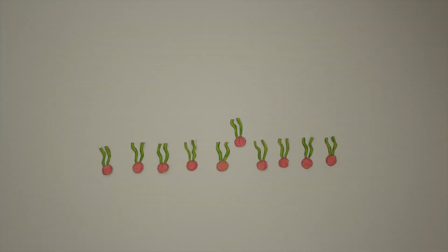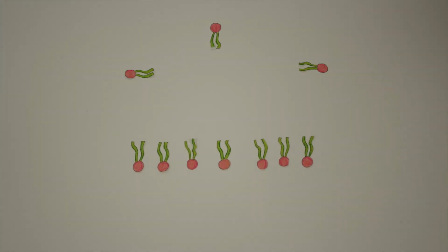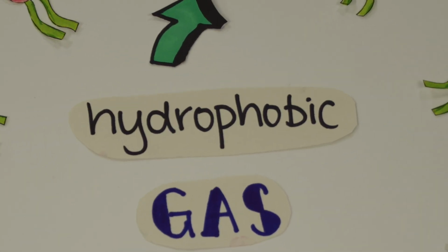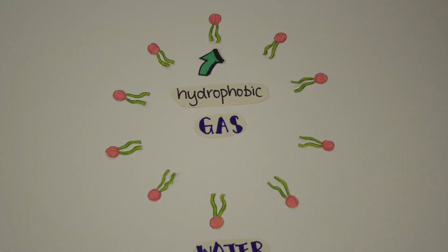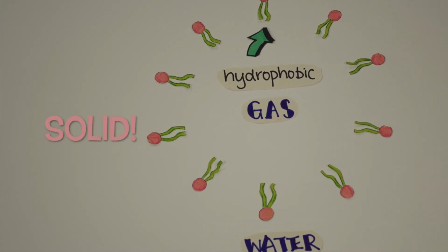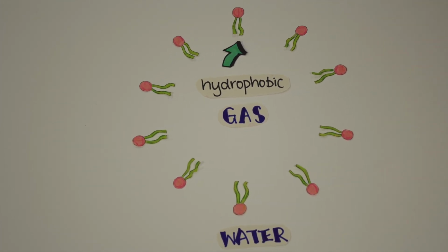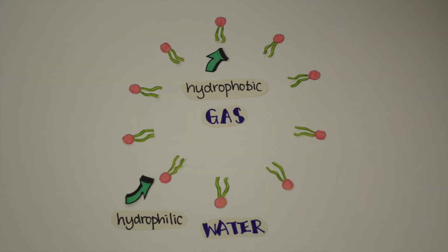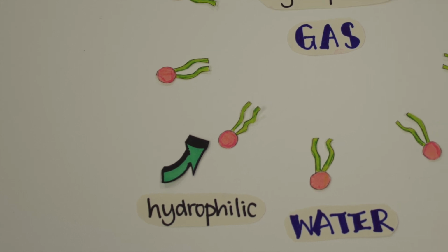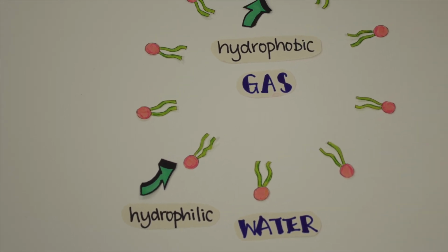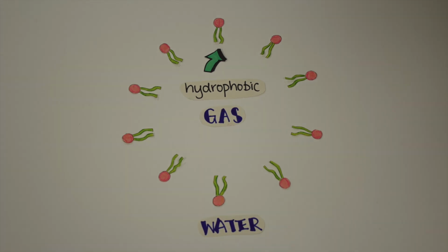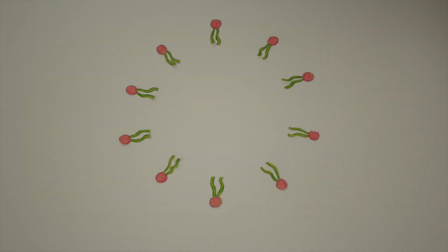For example, phospholipids self-assemble into a monolayer at the gas-liquid barrier, which is held together by the hydrophobic and van der Waals interactions between the tightly packed acyl chains, thus giving the shells solid properties. Their hydrophobic acyl chains face the gas, and their hydrophilic head groups face the water. Consequently, the lipid monolayer will form spontaneously around a gas bubble. The low surface tension reached by the lipid monolayer stabilizes the microbubble.